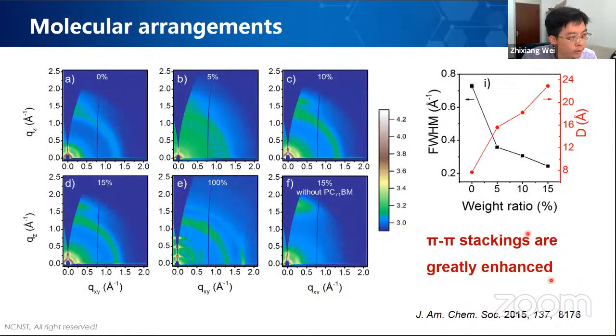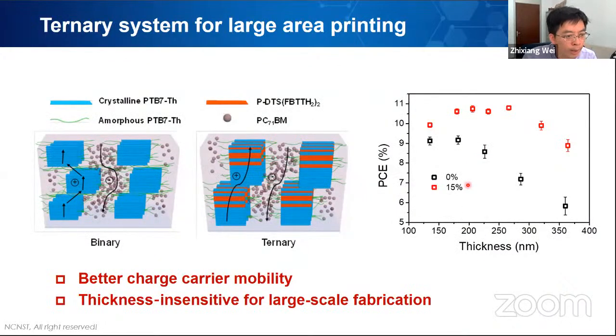The reason is that after adding the small molecules, we increase the crystallinity of the active layer, and you can see the pi-pi stacking is increased. Therefore, the charge transport is better. With this, we can compare the binary and the ternary systems. Using binary, normally the efficiency is reasonable at 100 nanometers. But if you increase the thickness, because of the loss from traps in this active layer, the efficiency decreases very fast. But in the ternary strategy, because the crystallinity is much better, it is not that sensitive to the thickness.